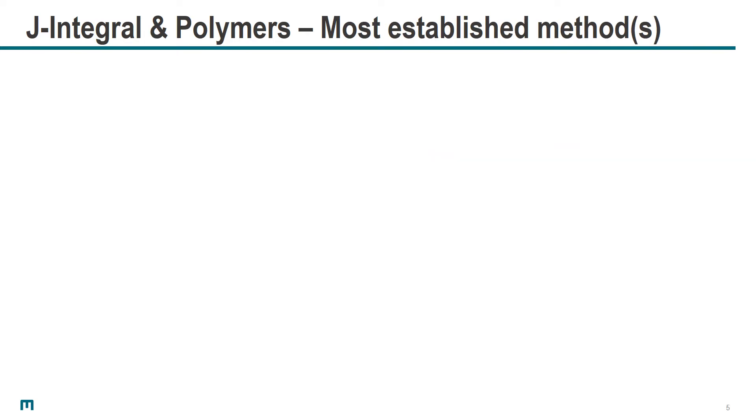Additionally, we cannot apply a classic load-and-unload method because our materials are highly time-dependent, as shown here on the right side with polypropylene. We have highly non-linear and hysteretic behavior, and therefore the results depend highly on the unload and loading rate and usually do not provide reliable results.